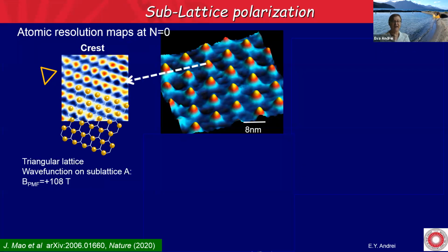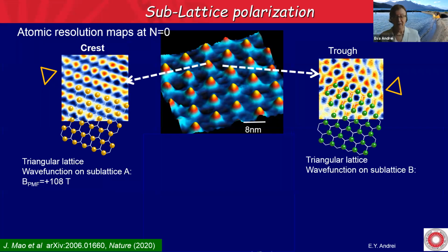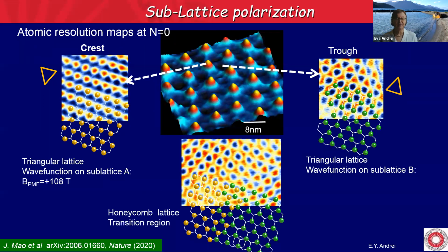Here we're sitting on the apex, on the crest, and we see indeed, we no longer see the hexagonal structure, we see a triangular structure, a triangle that's pointing down. That's telling us that the wave function is sitting on one of the sublattices. And now we're going to the trough region, and now the triangles point the other way. If we go to the transition region in between the two, we recover the honeycomb structure. So this tells us that the direction of the pseudomagnetic field is opposite in the two sublattices.